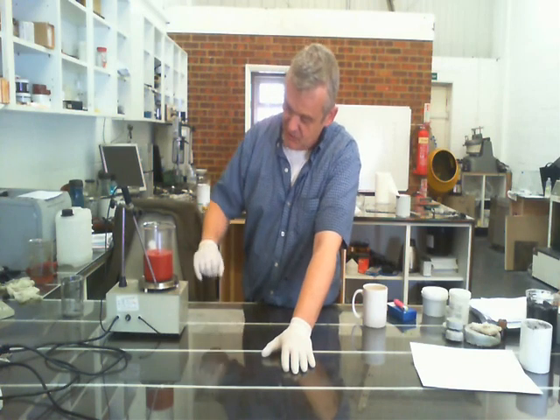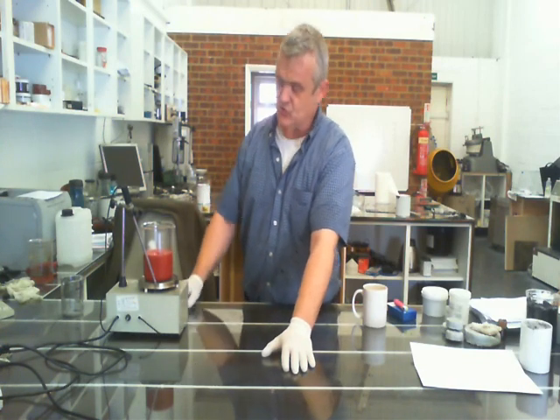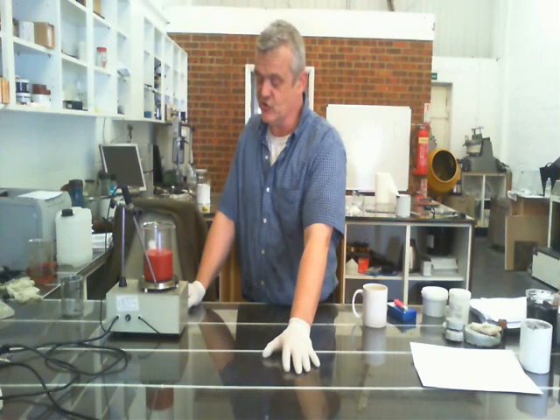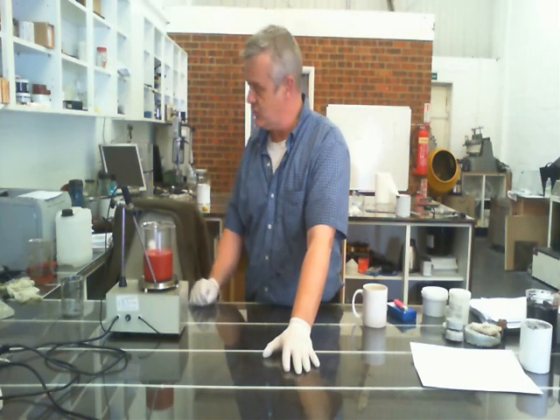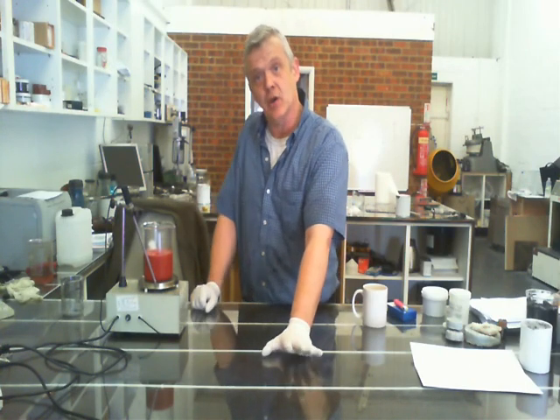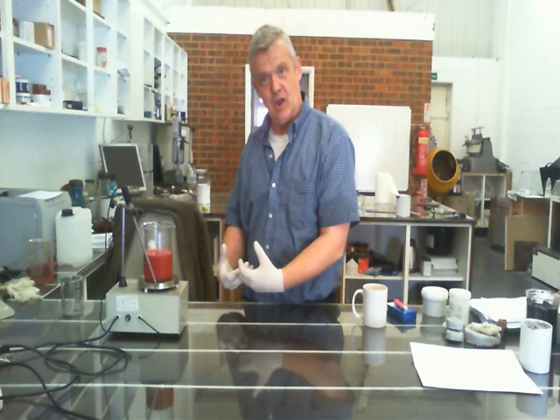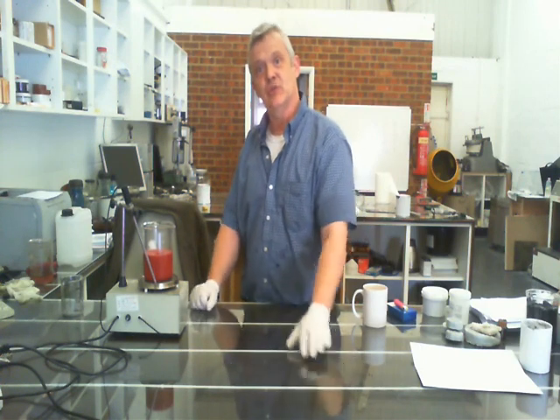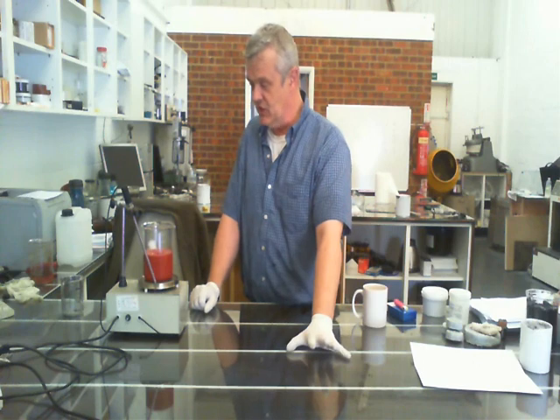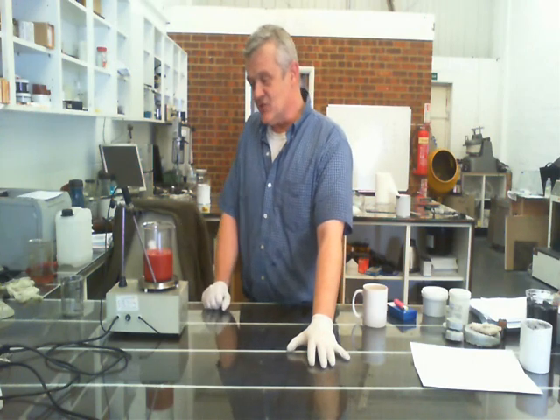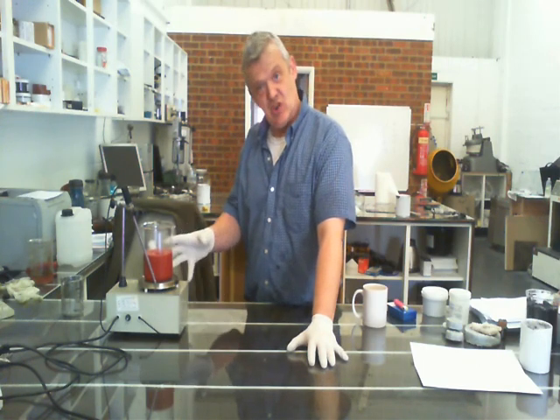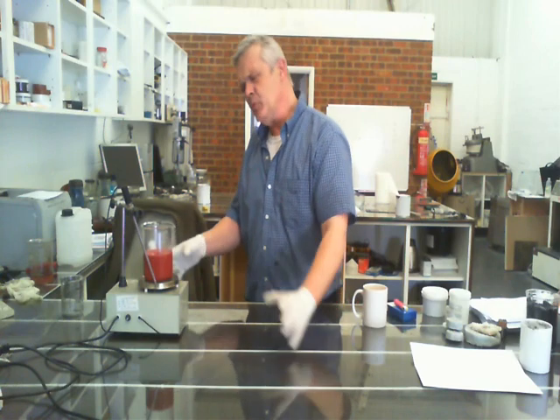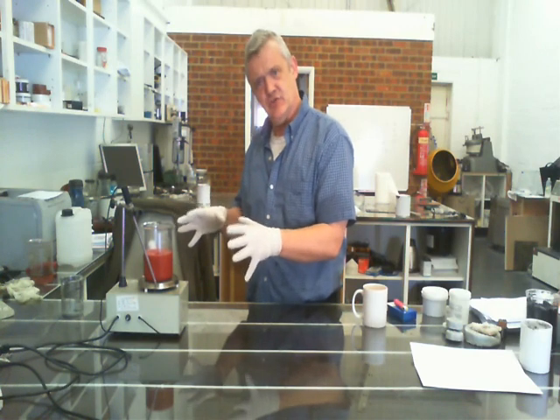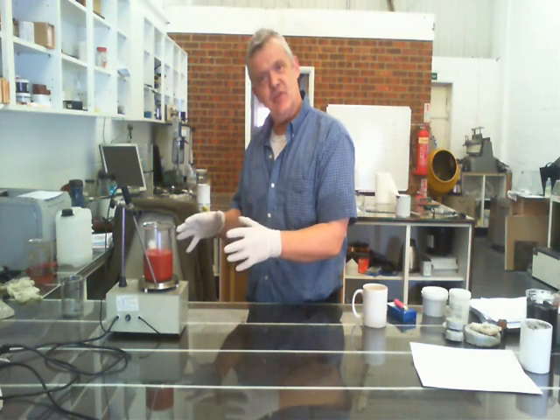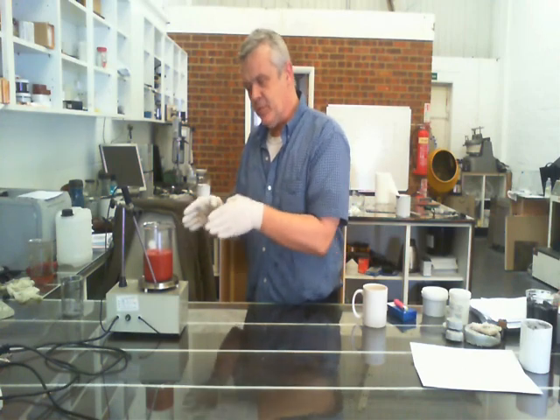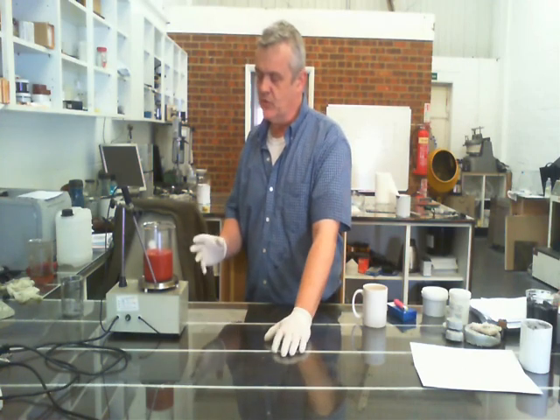So when I made this previously, this is exactly the steps I took, and that was just a colour comparison. So this thing will stir away for about 6 hours or so, going through those colour changes until it goes into that pink colour. When it got to that pink colour, that's a sure indication that you've formed copper particles. Now, there is something really interesting about this, is that I don't actually have to leave it to stir. Because it's quite a strong gelatin solution, it's actually quite self-limiting for its expansion. So I can put this into the microwave, which is what we'll do in a minute.